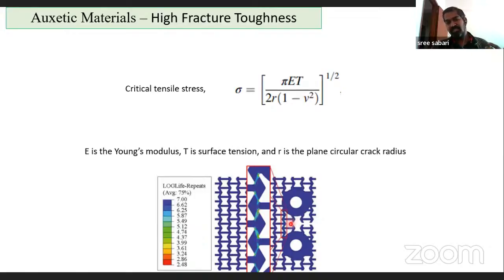But in conventional materials, if you have a crack, you will have a continuous material which is deteriorated in that condition, which will pave a way to crack propagations or initiations. Whereas in this case, since it's a cellular material, there are a lot of chances to reduce the crack propagations.